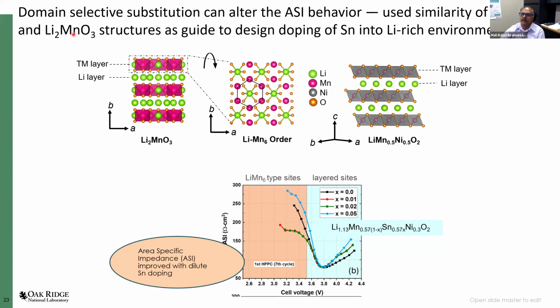And in fact, we were pleasantly surprised that this sort of thinking was actually correct, because when we put in a small amount of tin dopant, of the order of 1 or 2%, there is a significant flattening and lowering of the ASI, the area-specific impedance. On the other hand, if the doping level goes up, we see that it again becomes bad. So there is some critical small amount of doping that one can put into these materials to improve their low voltage power performance.